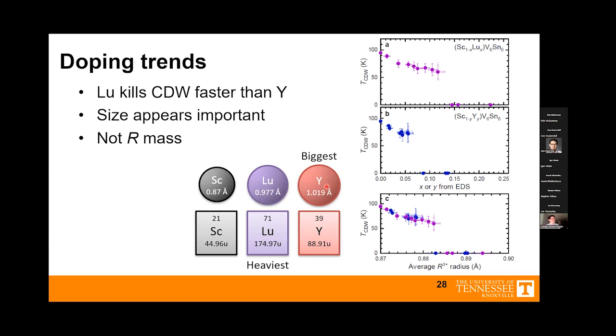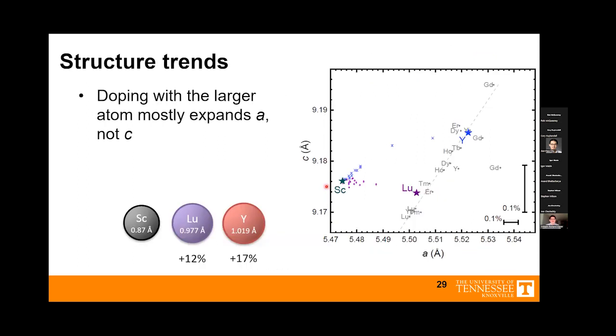If it was the other way around, if lutetium killed the charge density wave faster, it would suggest that that heavy lutetium atom was more important. And that would be kind of counterintuitive anyway. Scandium's the lightweight atom. It should have the highest energy phonons. So size matters here. That tiny scandium atom is what's allowing the charge density wave to form. And there's more evidence for this.